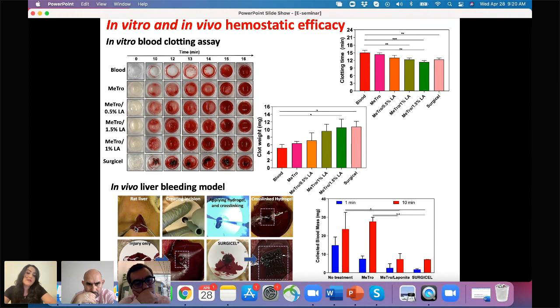And for this experiment, we create a defect on the liver with a biopsy punch, and then we seal the defect with our hemostatic biomaterials, and then we use filter paper to collect blood from the sealed tissue. And here is the mass of the blood that we collected, showing that for the group that had no treatment, after 1 minute and after 10 minutes, we have higher blood mass collected as compared to the MeTro/Laponite and Surgicel. And also for the Metro, as compared to the nanocomposite hydrogel, the nanocomposite was more effective than Metro without nanoparticles.